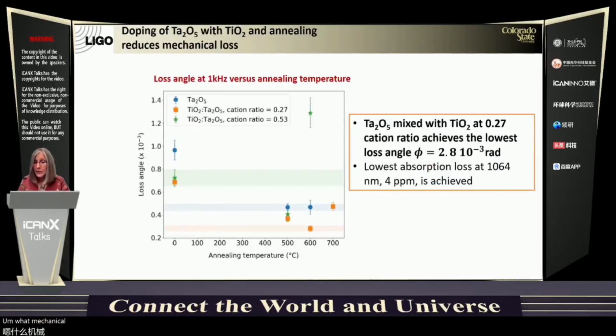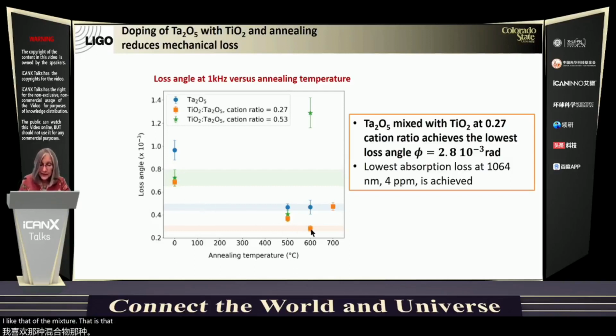What mechanical loss measurements revealed is that the mechanical loss of the doped samples is lower than that of tantala, but the alloy or the mixture that achieves the lowest mechanical loss is the one that contains 27% titanium content. And this result is consistent with what has previously been measured in titania doped tantala. Just to give you an idea, the optical quality of these mixtures is excellent. We measured 4 parts per million absorption loss in the 27% titania sample at 600 degrees C annealing.